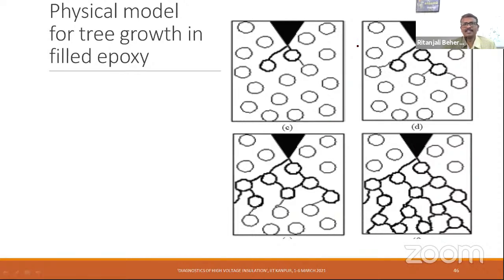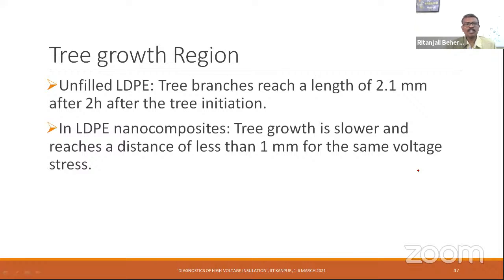This could be the physical model. What could be taking place here is that the darker line shows the movement of the charges, or the route for charges. They come and they get completely accumulated over the fillers. In fact, these light ones are the fillers. They are also fillers, but this one actually has the charges surrounding the interface between the filler and the polymer. That's what is taking place here. So as the charges move, they get attracted by the fillers, and it takes more time for the tree to reach its opposite electrode.